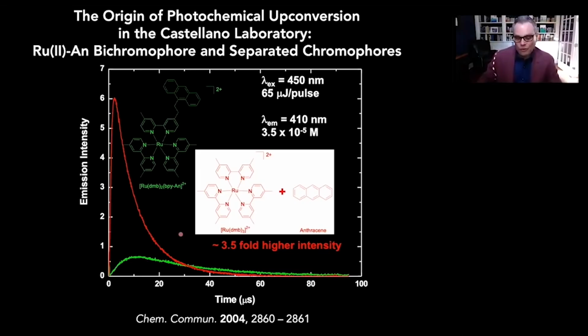So before we really embarked down this pathway, we made this model compound and we excited it selectively. This is with a nitrogen pumped dye laser, which is 65 microjoules per pulse, but these are picosecond laser pulses, so there's a lot of power. And what we immediately noticed was, exciting these towards the green.